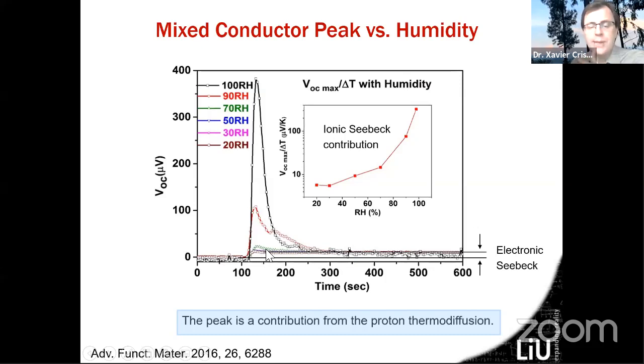Now, when the sample gets more and more humid, you see that this peak is growing, because the ions kick in. So you have the ions that start to move, and then there is a reorganization of both ions and electrons in the material that makes this drop here. Eventually, there is still a potential difference developed after some time, and this corresponds exactly to the electronic contribution of the Seebeck voltage.